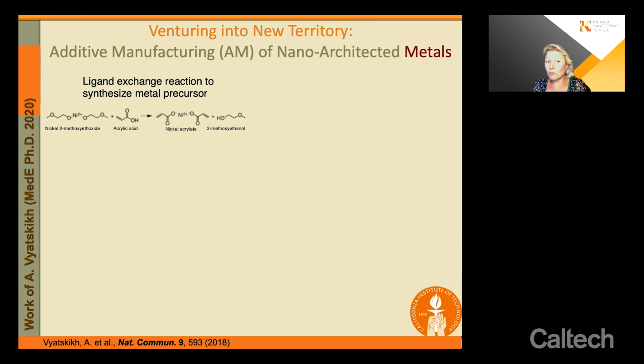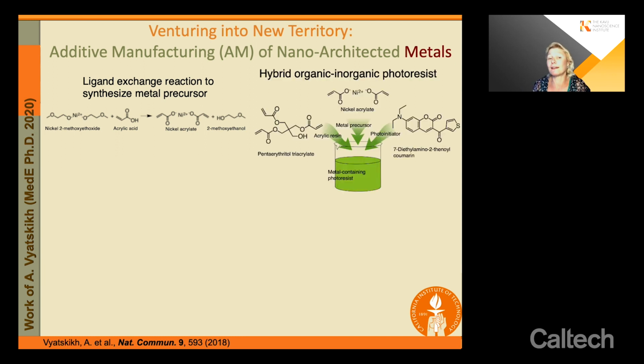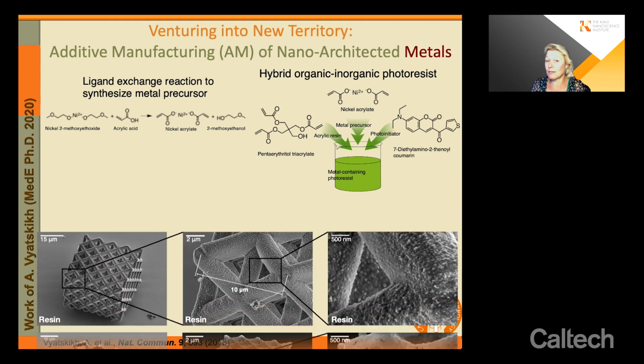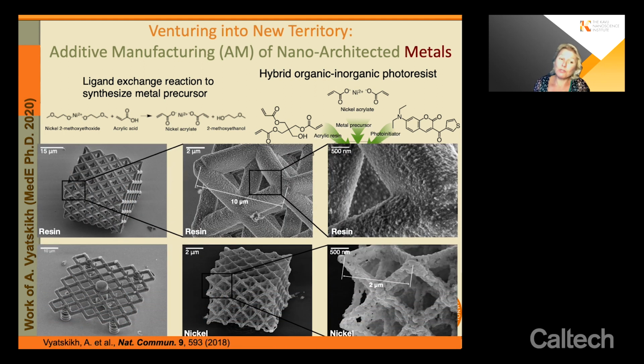And as long as we have enough of an acrylic type cross-linking capability within our chemical cocktail, so to speak, we should be able to write these architectures using these metal containing resins. Well, sure enough, so what you see here is the top row are these nickel containing resin architectures, and look at the size of the unit cell here. So this is on the order of 10 microns.